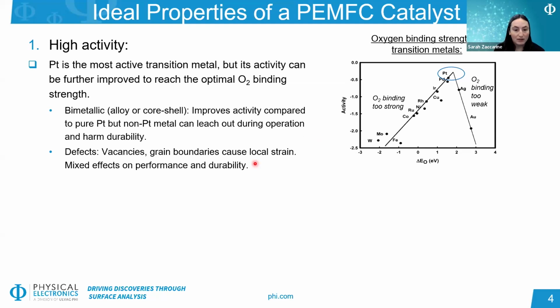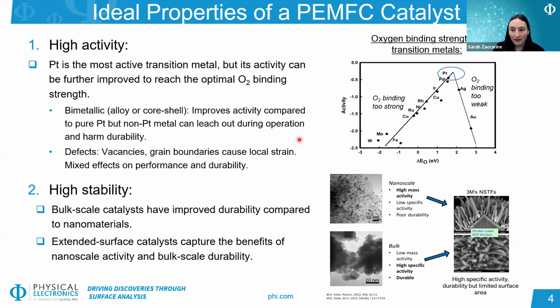Defects can also be used to tune the performance of these catalysts by inducing local strain in the platinum metal through things like vacancies or grain boundaries. This can be used to improve performance, but it's a trade-off that can have mixed effects if it's not incorporated in an optimal way. And then, of course, we also want high stability.